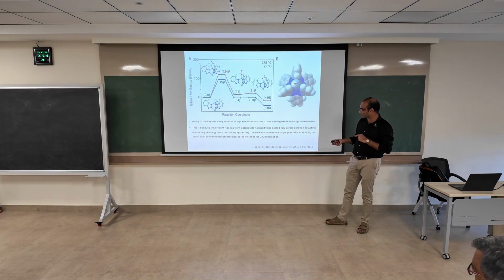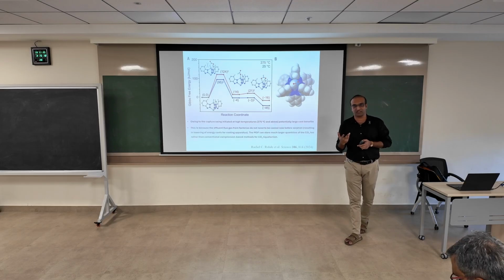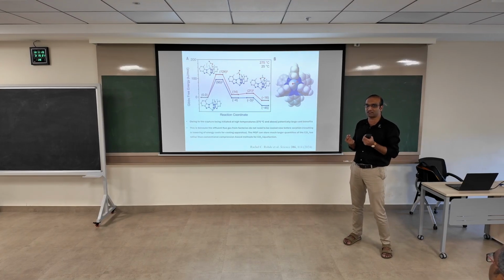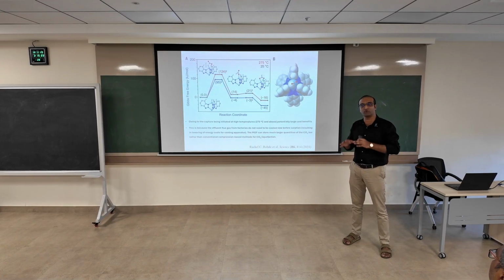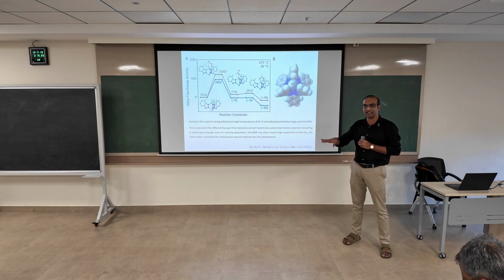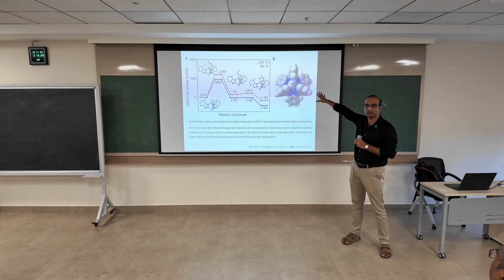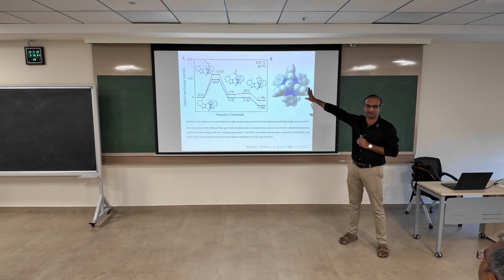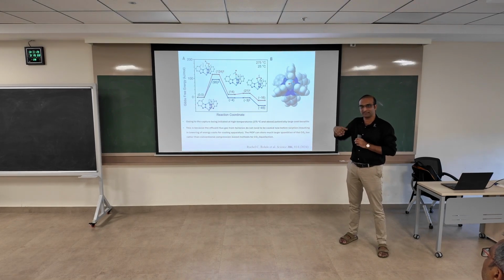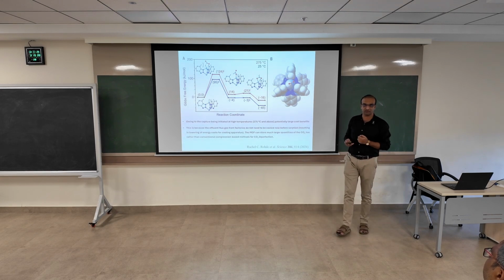So this particular MOF was published in Science because of its usefulness. Again, you're saving the energetics of the process where you don't have to cool the flue gas. It's coming right out, you don't even have to purify that gas. Whatever is coming in, only the CO2 will adsorb on this at 275 degrees Celsius, because at that temperature, the energy requirements are met to overcome any thermodynamic barriers.